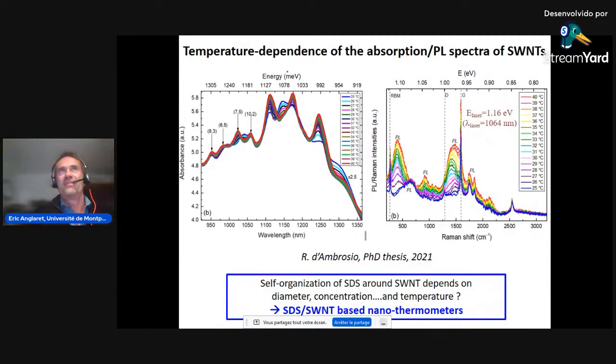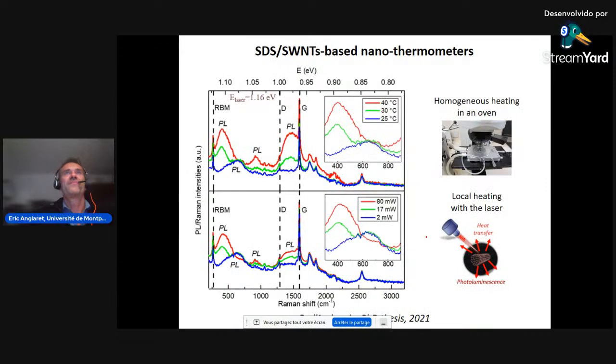So what you can see is that when you change the temperature on these nanotube SDS suspensions, you also observe some significant change in luminescence. You can see that the photoluminescence peak both shifts and changes in intensity. And what you observe as a function of the temperature, you can also observe as a function of the